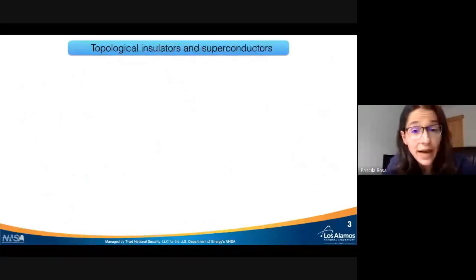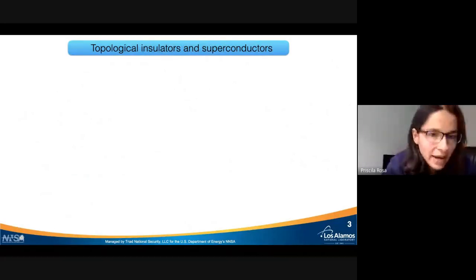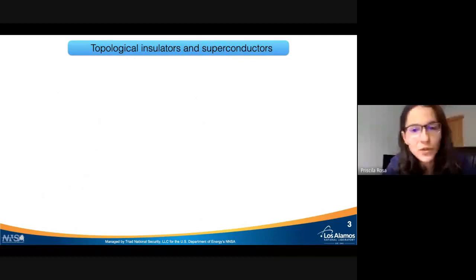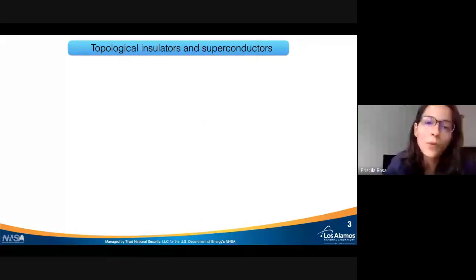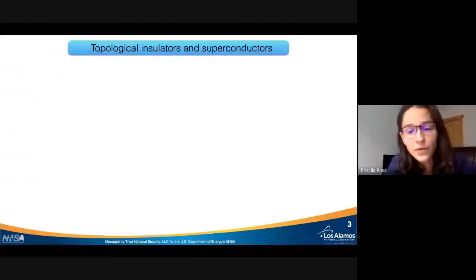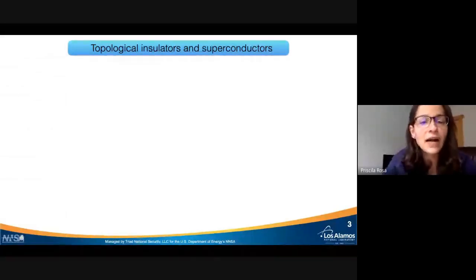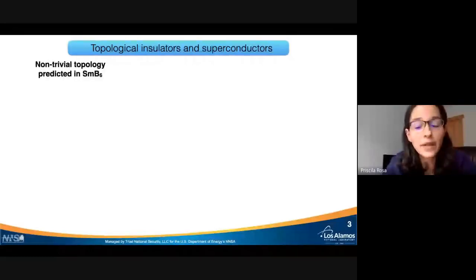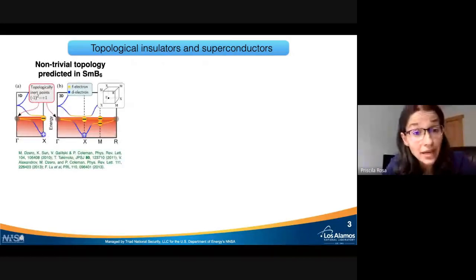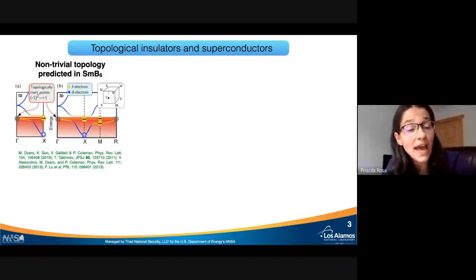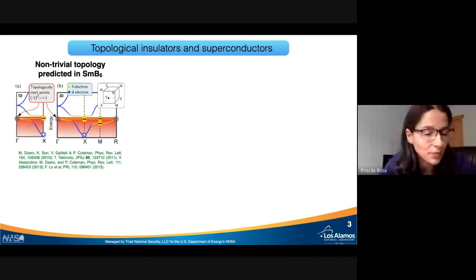So there are two types of materials that I'm going to talk about today, and they go from one end of the spectrum to another, very extreme end. One of them is insulators, and the other is superconductors. So starting with insulators, in 2010, samarium hexaboride, SmB6, which is a correlated insulator. There are strong electronic correlations here because of the f electrons of samarium. This material was predicted by various groups to be a topological insulator.